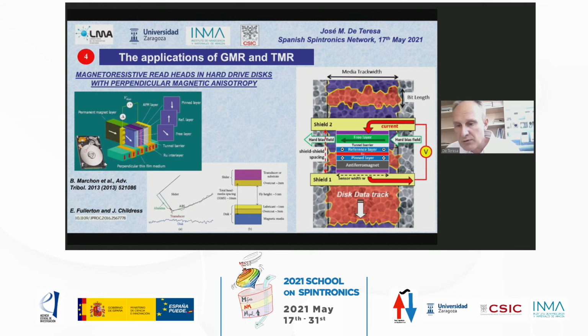And this is a top-down image of the read head on top of the track, of the bit track. So the bit length is as small as this one, as I mentioned, 10 nanometers or less nowadays. So it just contains a few grains of the magnetic material. And then you have here the magnetic tunnel junction. The magnetic tunnel junction is composed of the free layer, and then the tunnel barrier, and the second ferromagnetic layer.